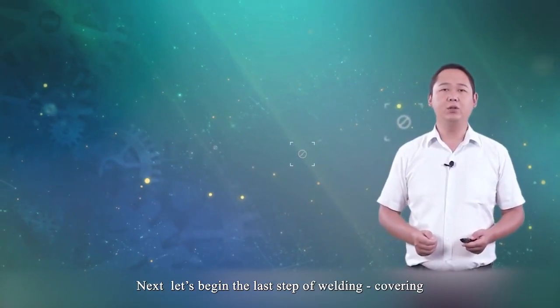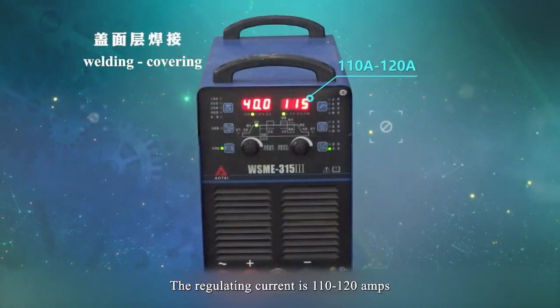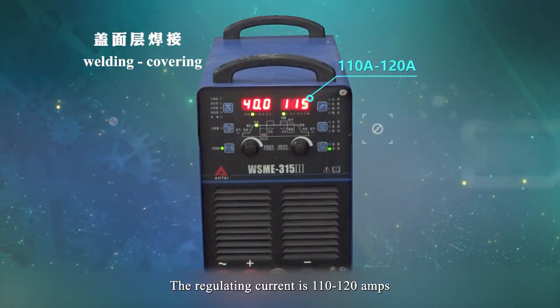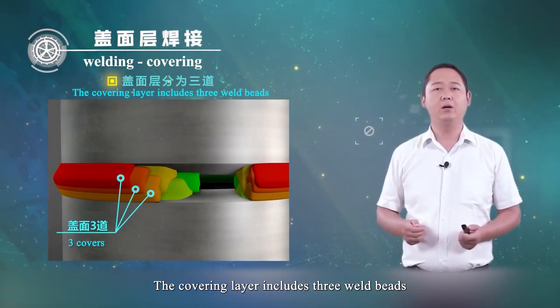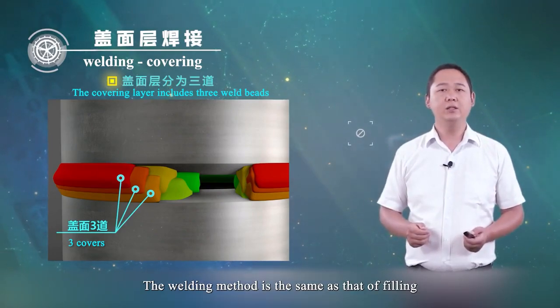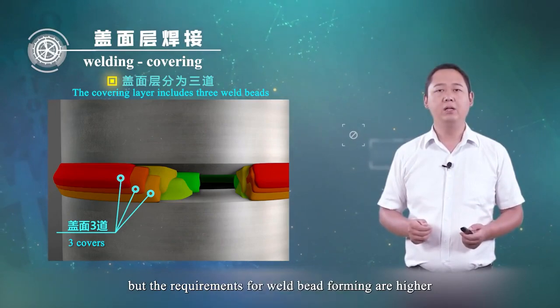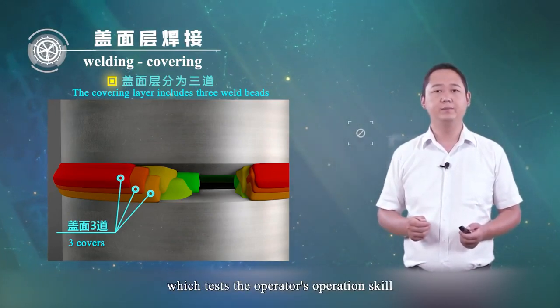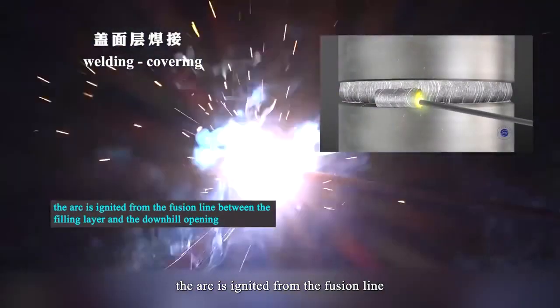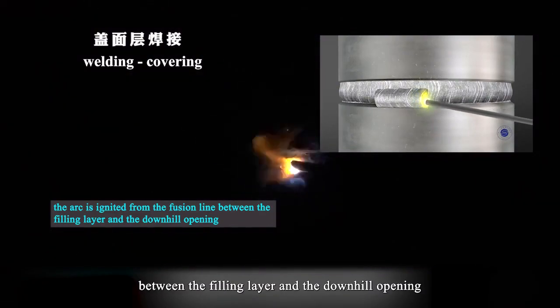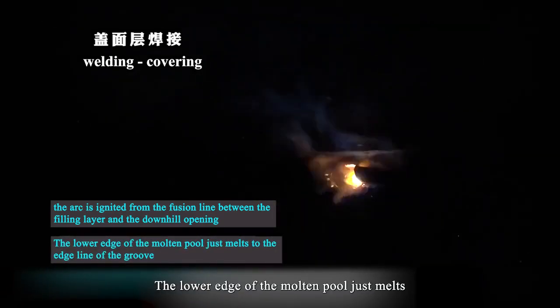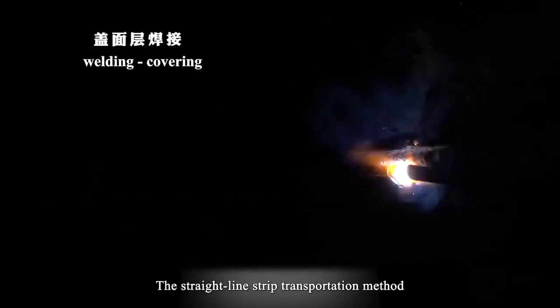Next, let's begin the last step of the welding, covering. The regulating current is 110 to 120 amps. The covering layer includes 3 weld beads. The welding method is the same as that of filling, but the requirement for weld bead forming is higher, which tests the operator's operation skills. For the first layer, the arc is ignited from the fusion line between the filling layer and the downhill opening. Short arc welding is adopted. The edge of the molten pool should just melt to the edge line of the groove. The straight line strip transportation method is adopted for the welding. Pay attention to the shape of the molten pool and adjust the angle in time.